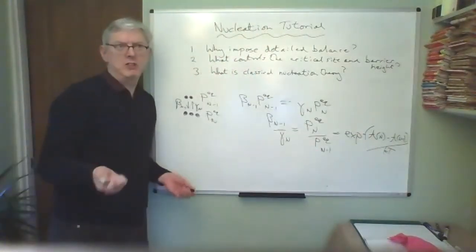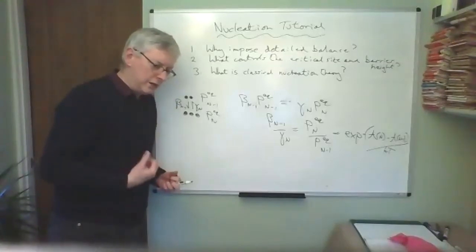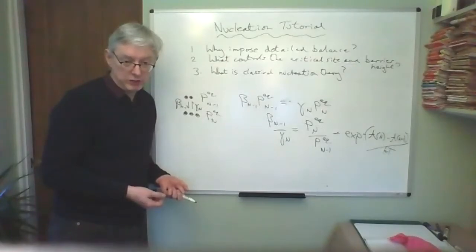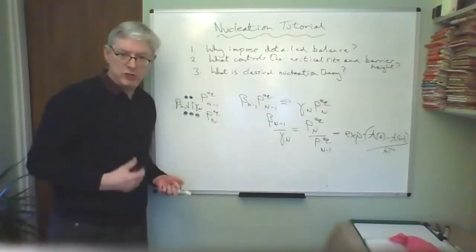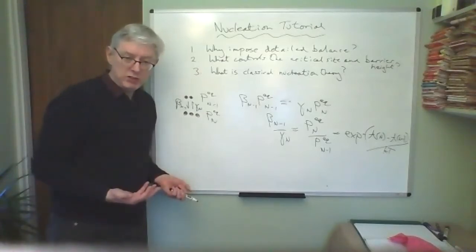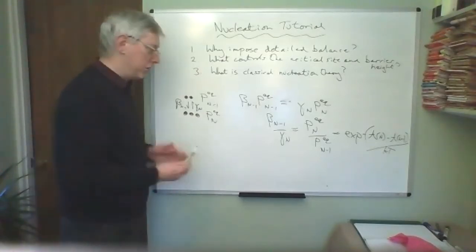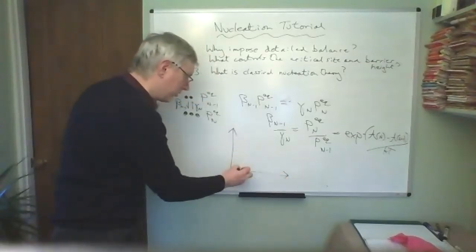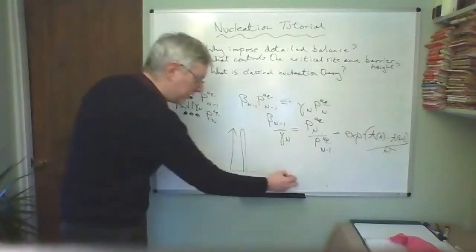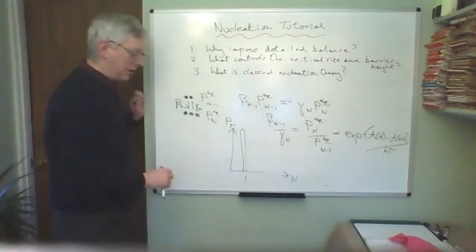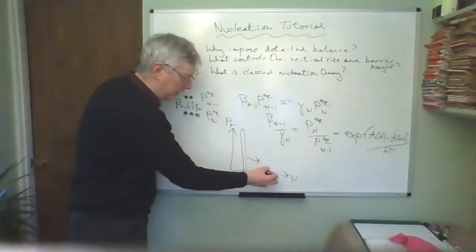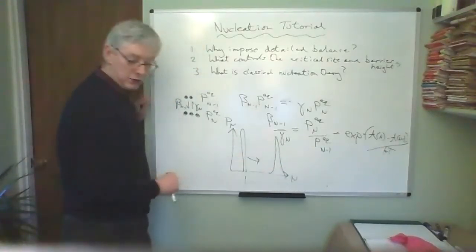And this is the answer to my earlier point. What can equilibrium thermodynamics tell us about a non-equilibrium process? It can tell us the ratio of these rates in a stationary situation. We can use those rates in a non-stationary situation when, as I've already discussed, we start out with probability at, say, monomer sizes, this is n, this is probability of n, we start out with a probability at monomers only, and it evolves until we have some distribution at larger sizes.